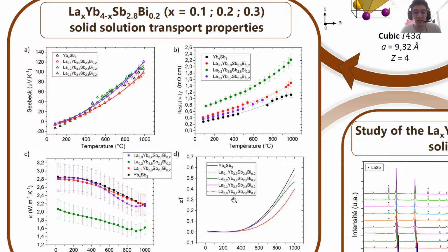These materials are quite sensitive regarding oxidation, so this is why I had to measure in two times mainly. And for the mother material, all the values obtained are really higher than the previous work. With the doped material, all the Seebeck coefficients remain in the same kind of range, and the Seebeck coefficient is not significantly improved by the doping on both sides here.